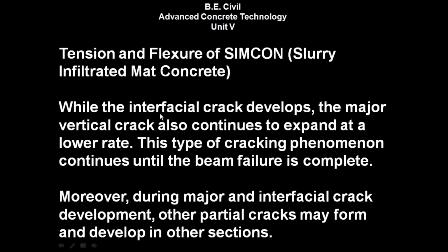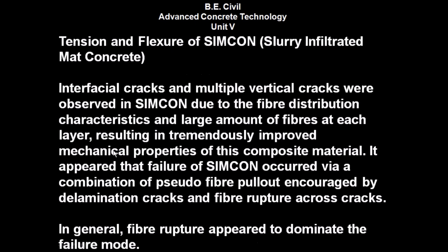While the interfacial crack develops, the major vertical crack also continues to expand at a lower rate. This type of cracking phenomenon continues until the beam failure is complete. Moreover, during major and interfacial crack development, other partial cracks may form and develop in other sections. Interfacial cracks and multiple vertical cracks were observed in SIMCON due to the fiber distribution characteristics and large amount of fibers at each layer, resulting in tremendously improved mechanical properties of this composite material.